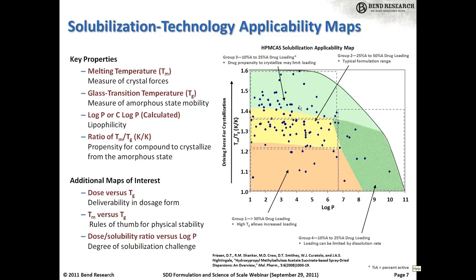And so, as such, oftentimes what's done in formulation, if you formulate these as a dispersion, is to go to fairly low drug loading, typically 10 to 25% drug loading in the dispersion. And in the other corner of the plot, you have the very greasy molecules, very high lipophilicity, low crystalline forces, and in fact, in the extreme, some of these are oils at room temperature. The challenge there is not one of preventing crystallization, but rather getting rapid and extensive dissolution for something that's so hydrophobic, even when it's in a dispersion. So there again, sometimes you go to fairly low drug loading in the SDD, or in fact, there are a number of related dispersion technologies to increase surface area and dissolution rate that we sometimes use.